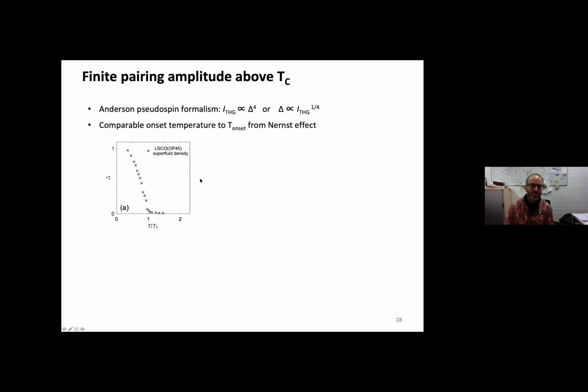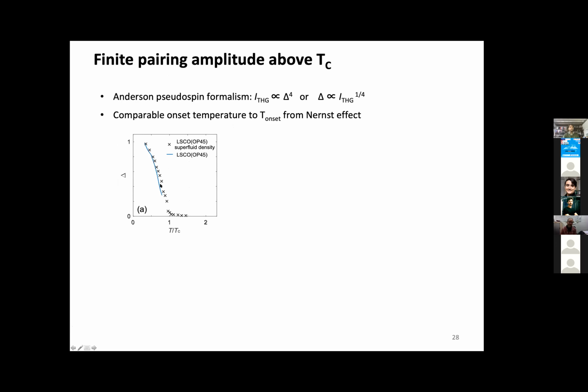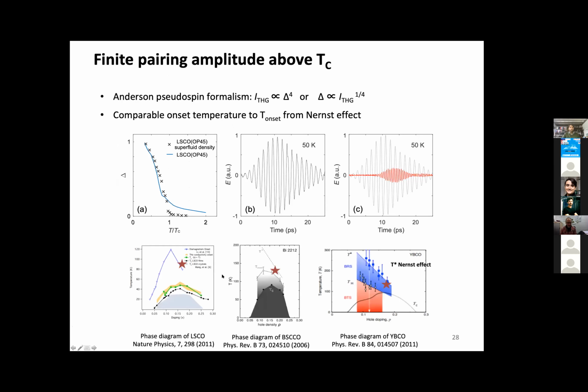And that brings me to the last interesting point here. If we compare now the intensity of this THG, one can show that it is linked by the fourth power to the superconducting gap. If we plot the superconducting gap measured with linear measurements, and map onto this the order parameter evaluated from our Higgs spectroscopy, then we are mapping this pretty well below TC, but above TC we are now mapping a finite response of the Higgs. And the interesting point is, this finite response, we map in the different classes of superconductors up to the temperatures where typically the Nernst effect is seen in the system.